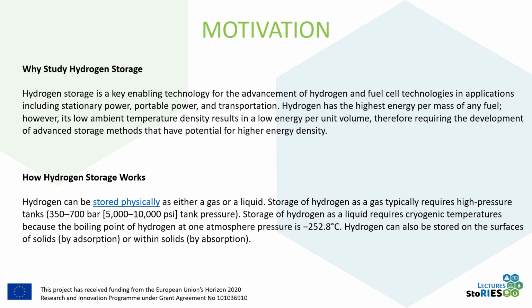However, it has a very low density at ambient temperature, and this results in a corresponding low energy per unit volume. This challenge underscores the necessity for innovative storage solutions that can achieve higher energy density. In general, hydrogen can be stored in several forms: physically, as either a gas or a liquid, and gas storage typically requires high pressure tanks operating at pressures between 350 and 700 bar. That's to say 5,000 to 10,000 psi.